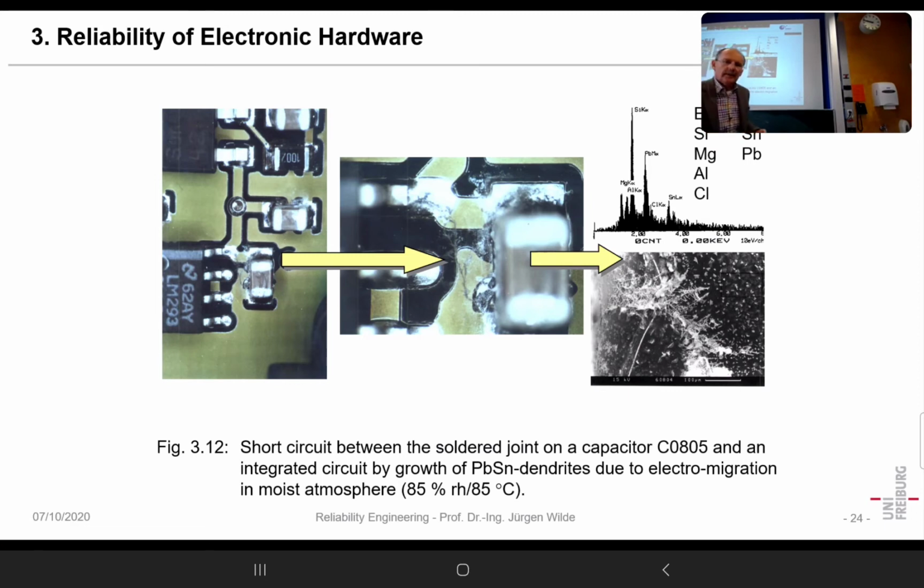And that's the reason why we first had a thin film of water, and in that film we had some kind of electroplating or electrodeposition process. Of course, in such an ECU, you have a voltage of 0 to 12 volts or 5 to 0 volts, but we have some voltage differences, and these lead to some electroplating.